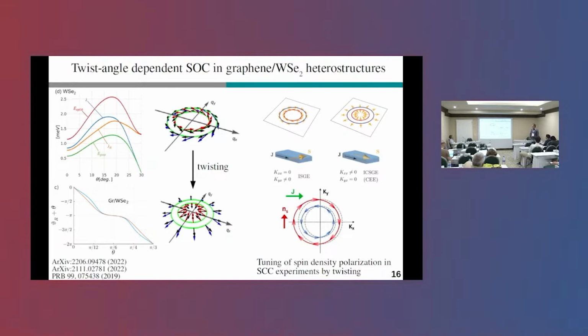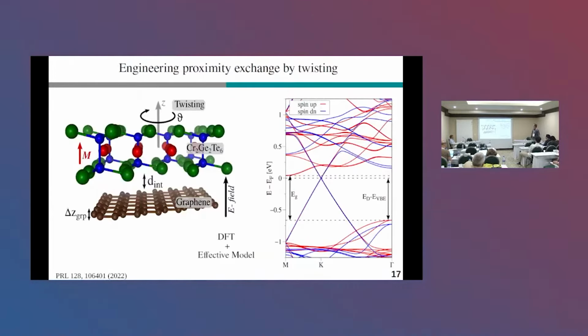And now let me switch gears and come to the actual things I would like to present, which is the engineering of proximity exchange in graphene chromium germanium telluride heterostructures by twisting. So the situation we have is like this. We fix the magnetization of the ferromagnet and simply twist. On top of that, we can apply a transverse electric field to see how the things can be tuned. And what we do is DFT calculations on large supercells, and then we do the effective modeling of the low energy states.